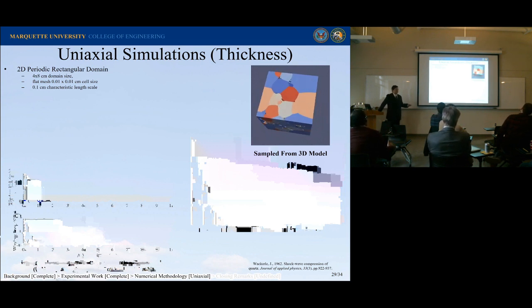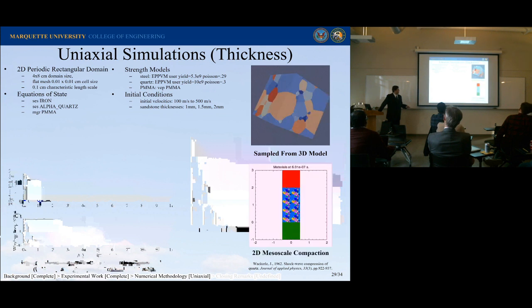So then I started to do some uniaxial simulations that were a little bit better. I built this 3D model in Dream 3D based off of the grain size characteristics from before. And then I sampled those, put in some equations of state, and gave some strength models based on quartz this time, since I'm giving the strength model to the grains rather than the whole body as a whole. Then I give it some initial conditions, and you can see right here, I have this impactor, and you now get compression of the grains as you go through and decreasing porosity, which is pretty awesome. And so let's go and compare it.